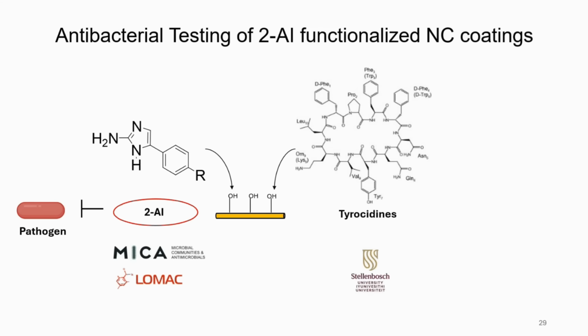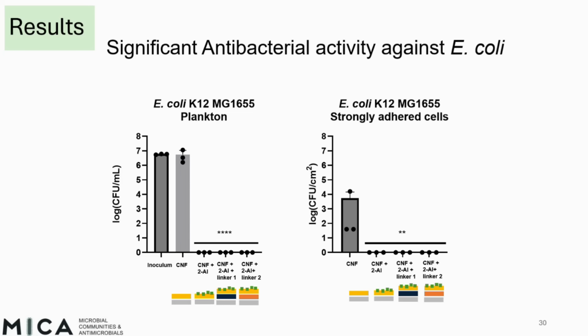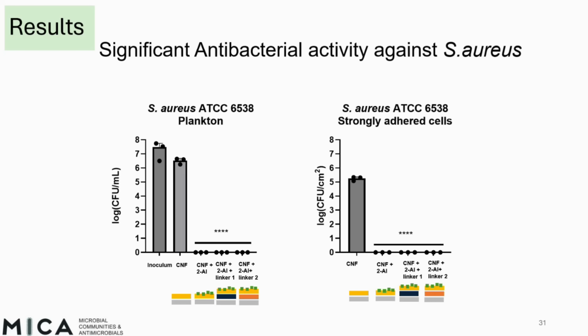First, we evaluated the activity of nanocellulose functionalized with the 2AI on coated glass against these pathogens, where we tested CNF on glass, CNF modified with the 2AI on glass, CNF modified with the 2AI with linker 1 on glass, and CNF modified with the 2AI with linker 2 on glass. And here we could see total inhibition of planktonic and strongly adhered cells on the coatings of modified nanocellulose compared to unmodified nanocellulose. We also saw the same activity against Staphylococcus aureus, which is the inhibition of all the planktonic cell counts and the strongly adhered cells compared to the unmodified control.